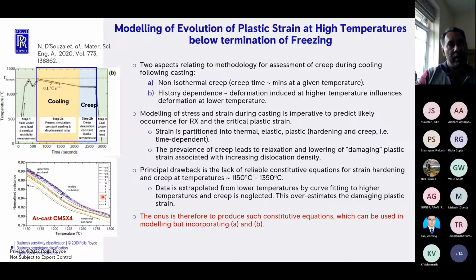At lower temperatures, where recrystallization is not that important in terms of the evolution of stress and strain, hardening becomes more important. But at higher temperatures, creep is one of the main deformation mechanisms. So you need to be able to produce a model, or a set of experiments to get you some data, that looks at some of the key aspects that relate to creep under these conditions. In terms of investment casting, there are two very important aspects that one needs to consider.